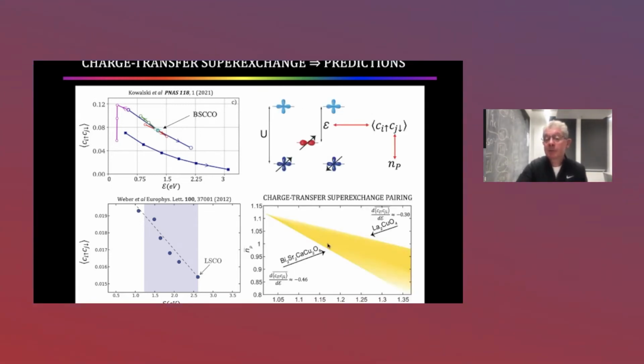And here we just summarized, in fact, this has been predicted for a range of materials now. So the horizontal axis is charge transfer energy, the vertical axis is normalized pair density, normalized by the ambient pair density that you would get for the standard parameters of each material. And that yellow cone there is the cone of interest. The theorists would say, if charge transfer superexchange is the mechanism, then if you do the experiment, the results should lie inside that cone.